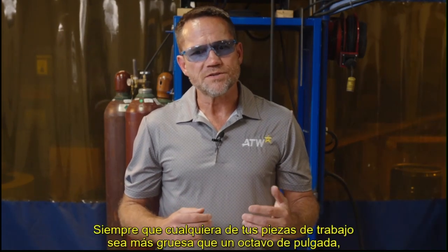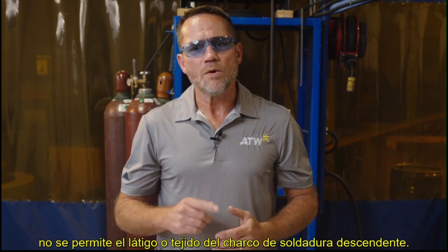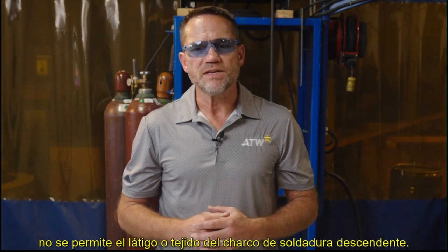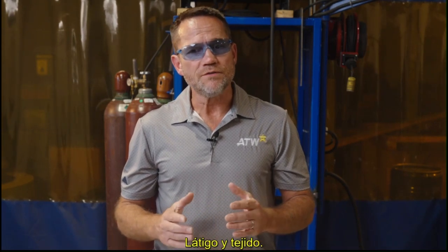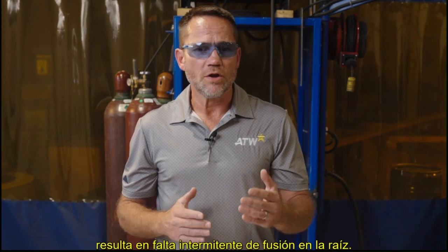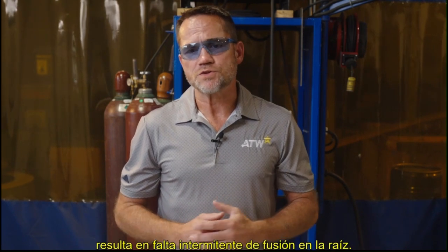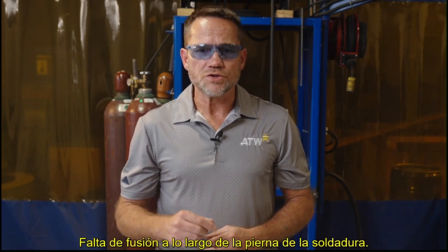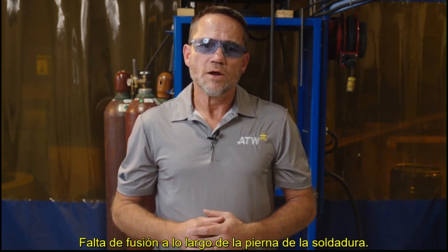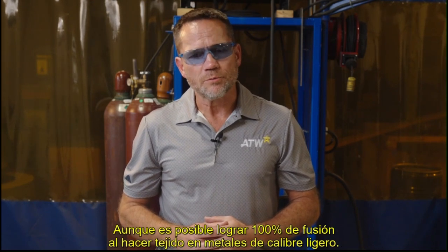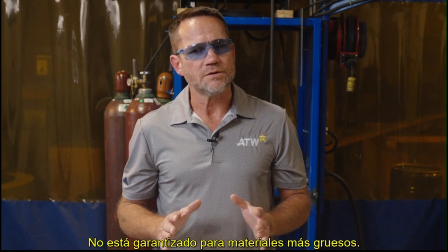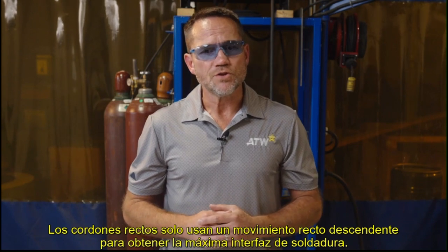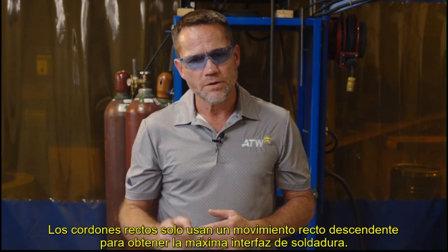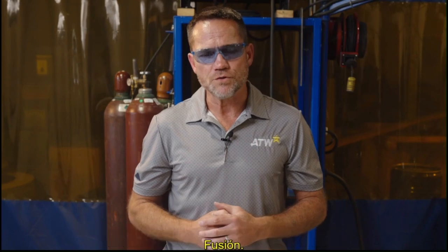Whenever either of your workpieces are thicker than 1/8 inch, whipping or weaving of the downhill weld puddle is not permitted. Whipping and weaving while welding downhill structural welds results in intermittent lack of fusion at the root, lack of fusion along the weld leg. While 100% fusion is possible when weaving on light gauge metals, it is not guaranteed for thicker materials. Stringer beads only. Use a straight pull downhill to get a maximum weld interface fusion.